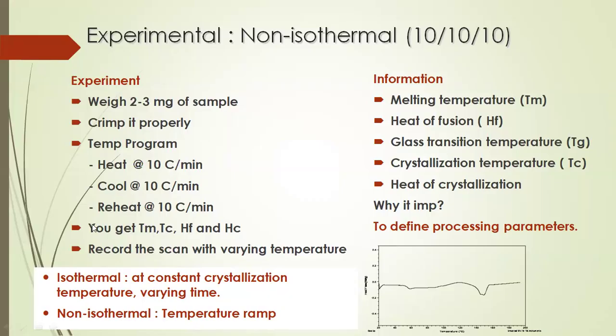Again, cool it at 10 degrees centigrade per minute and reheat at 10 degrees centigrade per minute. What information can you get from here? From this thermal analysis, you can get melting temperature, crystallization temperature, heat of melting and heat of crystallization. Here we record the scan with respect to temperature. It's important. Why? Because it defines your processing temperature. The processor, by looking at this scan, finds out that he should process the material at the melting temperature.